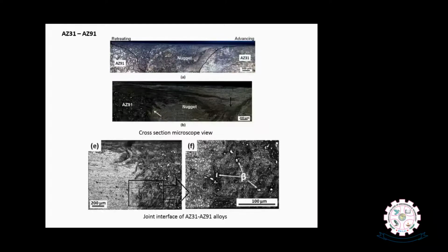You can see on the right side AZ31 and opposite AZ91, and the magnified images also show the nugget zone is free from any defects. A further magnified image of the cross section of the weld joint also shows the materials were properly stirred and a perfect metallurgical joint was achieved. Interestingly, the intermetallics which are present in AZ91 magnesium alloy before welding were distributed as small particles. The network-like intermetallic structure which we observed in the base material AZ91 was broken in the nugget zone into small intermetallics. So the advantage of decreased brittle intermetallics in the weld zone will improve the strength. Also, the smaller grain size improves the strength of the weld joint.